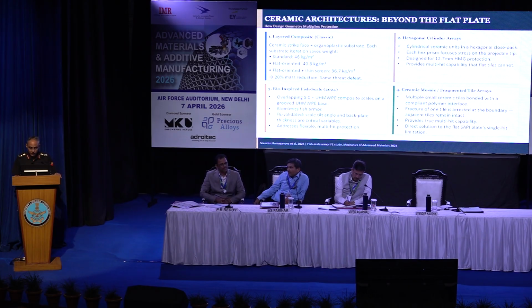Ukraine data shows that 2 to 3 impacts within 100 mm of radius is now a common scenario. Against a monolithic plate, the third impact is effectively unprotected. Against a mosaic array, it is not. India has no indigenized mosaic ceramic array in production or in qualified specifications. The ceramics, boron and silicon carbides are available. The funded qualification program is not. That is a research priority that will be flagged in the last.